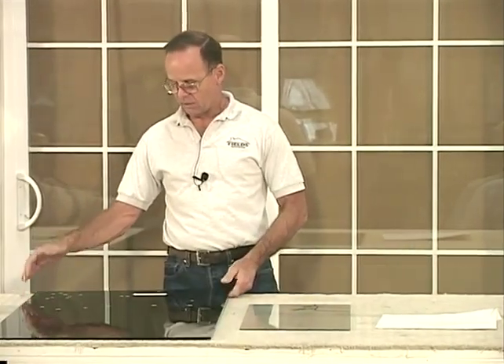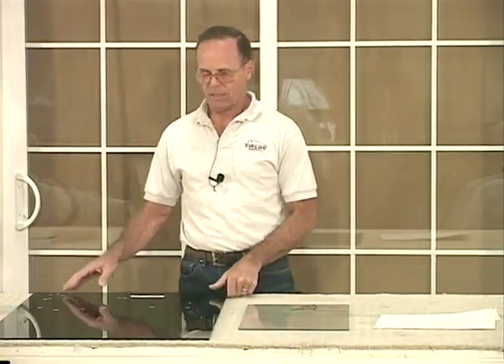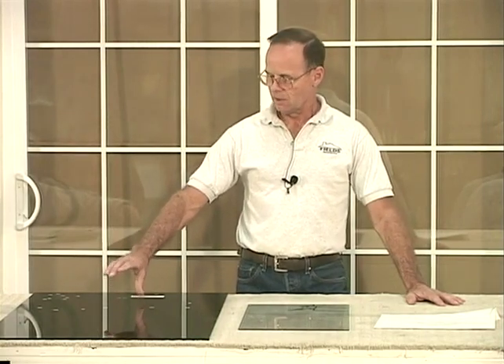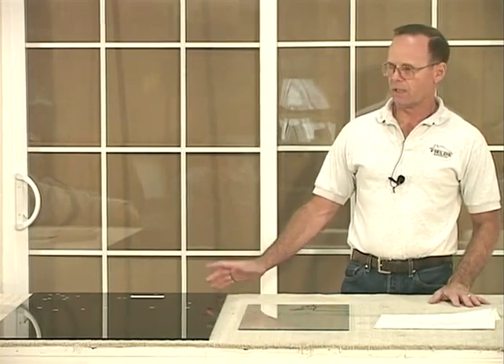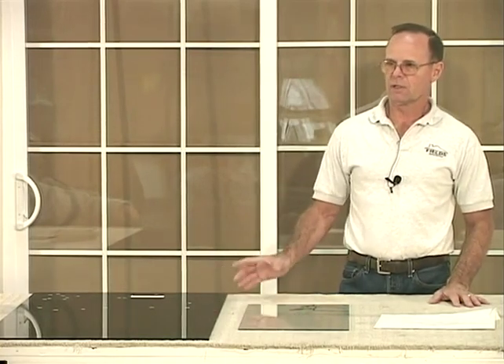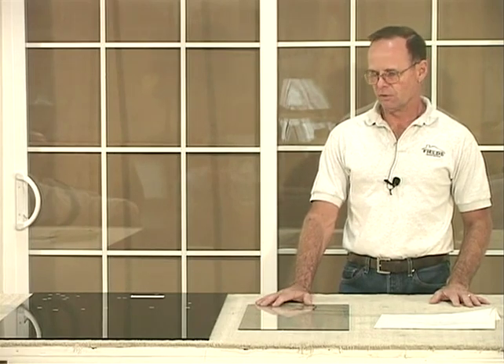And I actually used a UV lamp, and that's how you can tell if it's float glass or not. If you take a UV lamp and shine it on one side of the glass, and we'll do this demonstration, you'll get a grayish reflection. And if you shine it on the air side of the glass, you'll get a clear, crisp reflection. And this shows up much more on tinted glass than it does on clear glass. It still shows up on clear glass, but it's harder to see. And if you do it outside in the bright sun, it's even harder to see.